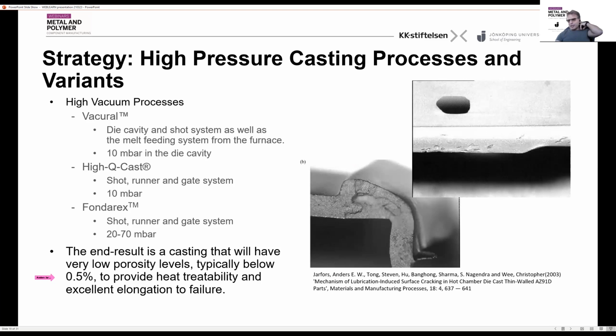Now, in all these processes, the die release agent can definitely cause a problem. And I would like to show you here one little example, because it's not only the pressure in the chamber that is important. This is from a study with a foundry that had a problem on rainy days, where you had a very large rejection rate on the rainy day, but on the sunny days, it worked like a charm. And it turned out to have to do with the evaporation rate in the die, and there were some clearances between different parts of the die where you had die release agent getting stuck.